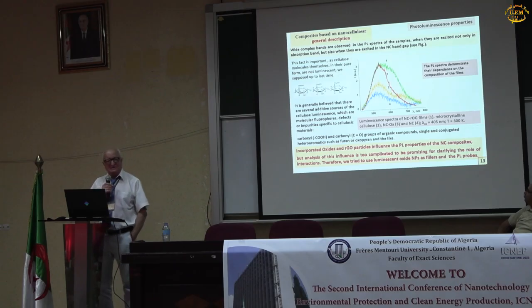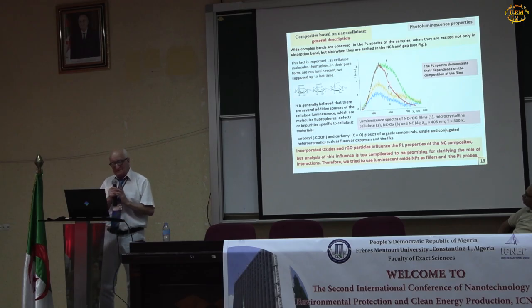We also use the luminescent method of investigation. We see a complex band of luminescence in the spectra, and they are excited not only in the absorption band but also in the band gap. This fact is important, as cellulose molecules themselves, in their pure form, are not luminescent, we supposed up to last time. It is generally believed that there are several additive sources of cellulose luminescence, which are molecular fluorophores, defects or impurities specific to cellulose materials: carboxyl, carbonyl groups of organic compounds, single and conjugated aromatics such as furan, oxyfuran, and so on.